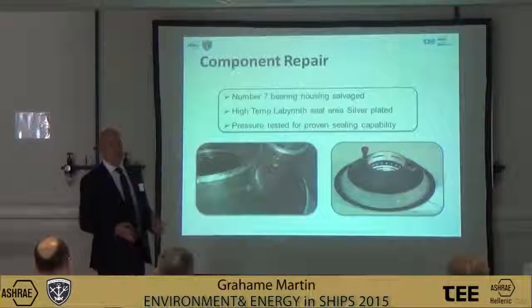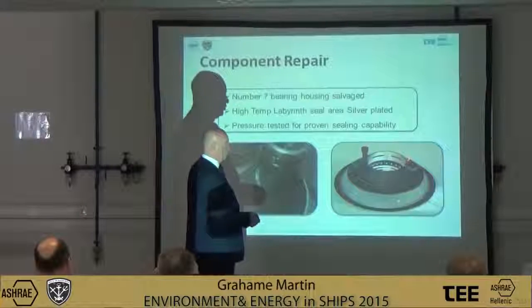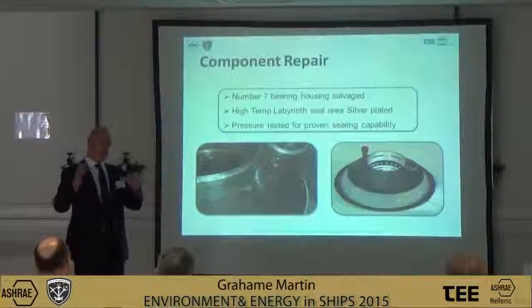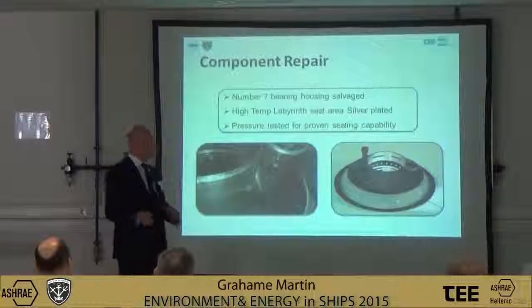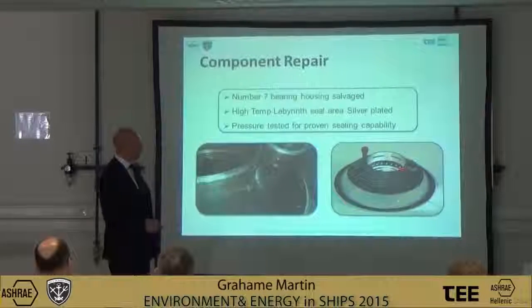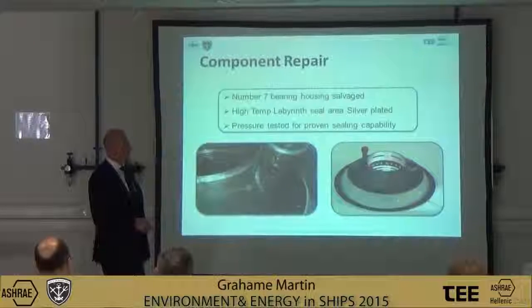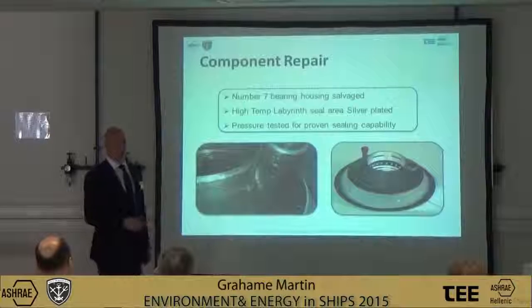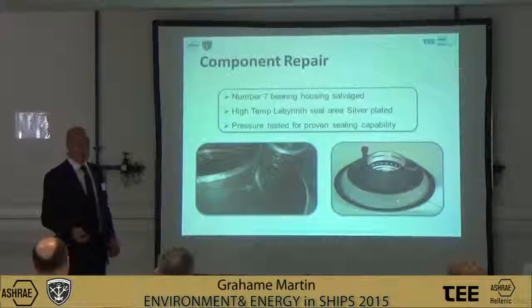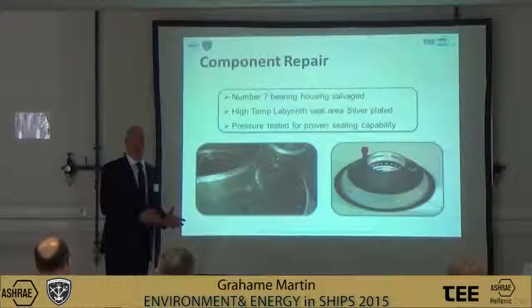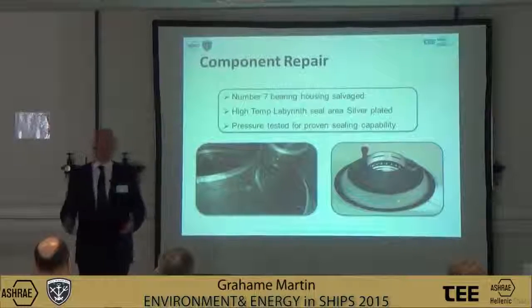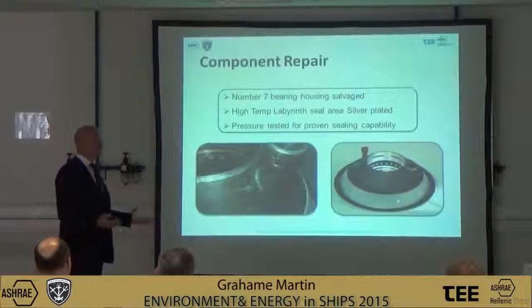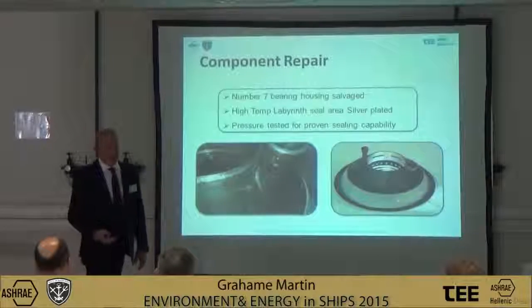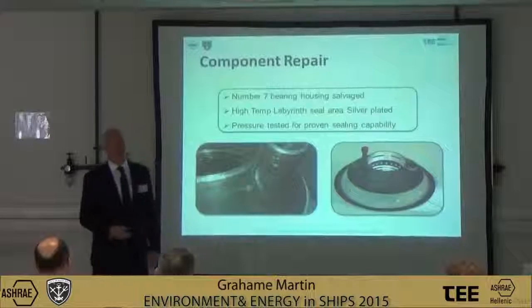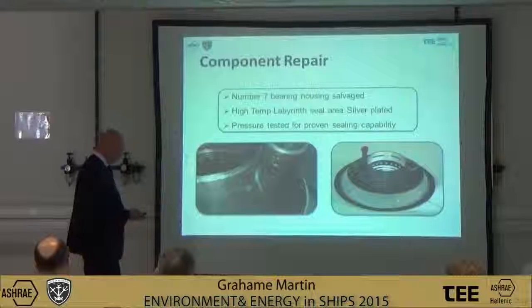And this is the component after overhaul. So we can, through our jigs and fixtures, make sure that the cooling elbow is still in its correct place. It needs to be for when you locate the turbine section onto the delivery case of the engine. But also, we have recovered the first stage turbine labyrinth seal area by coating it with a silver plating and then machining it back to tolerance so that, again, this is another component that could be released for a full service life. So when we talk about full service life, in the industrial world, that would be typically 24,000 hours of running, or for a marine application, we'd be looking at 13,000 hours of running.